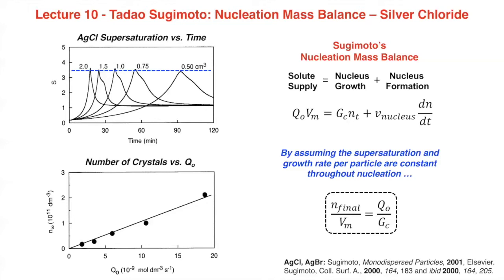Okay, so at this critical limit, the solute concentration stops changing, and so the solutes must either make nuclei or stick to existing nuclei. And because of this fact that the solute concentration is fixed or constant during the nucleation phase, it makes it possible to solve this nucleus growth part. This growth process here effectively becomes constant.